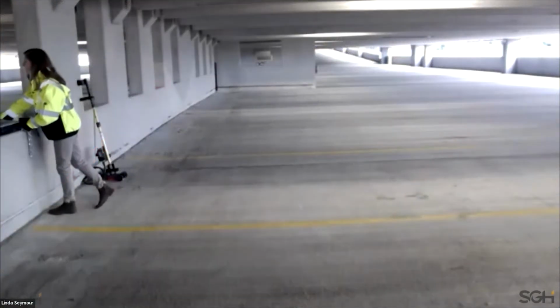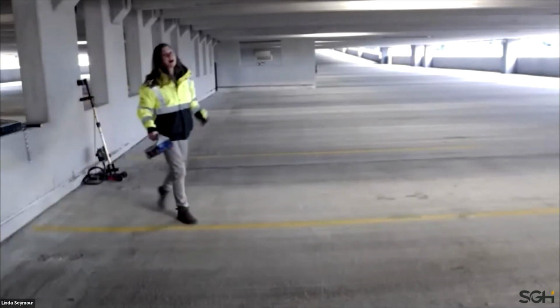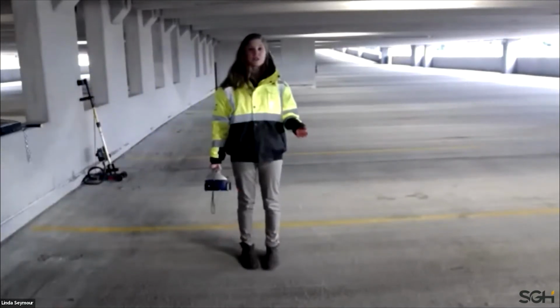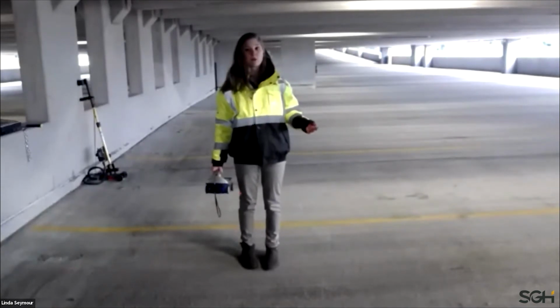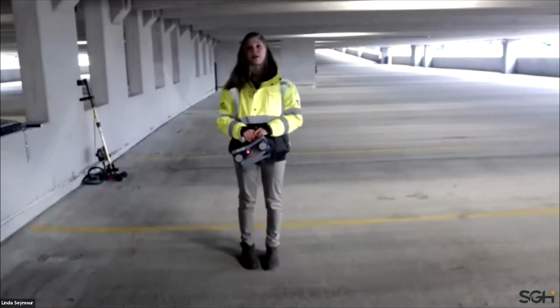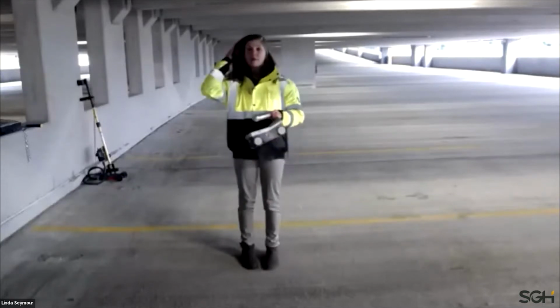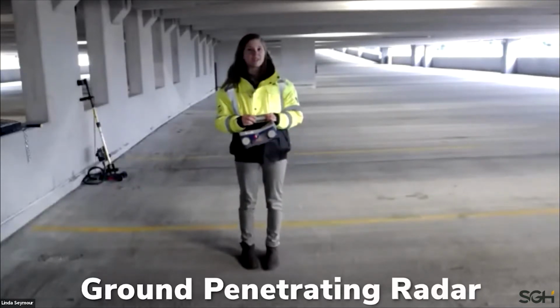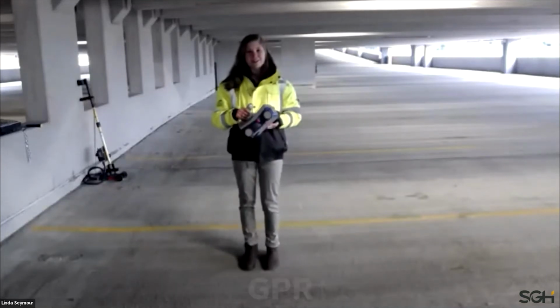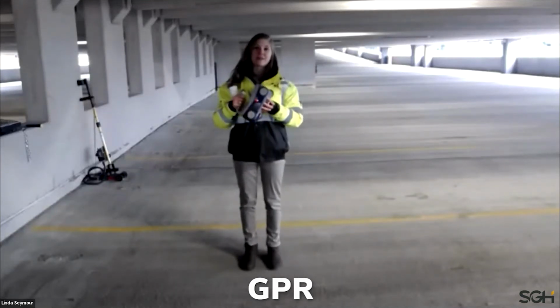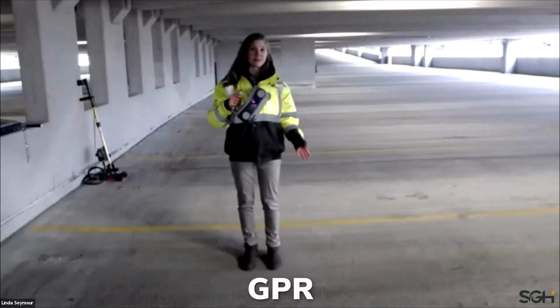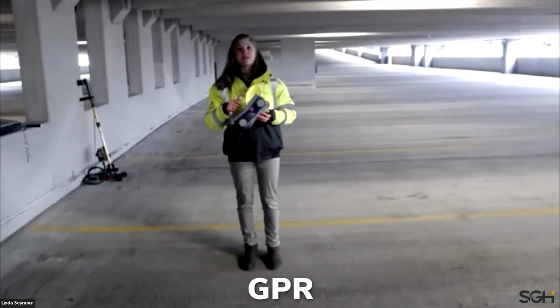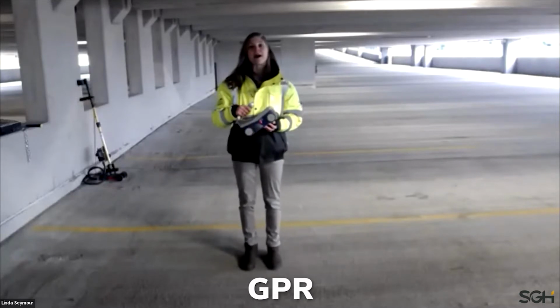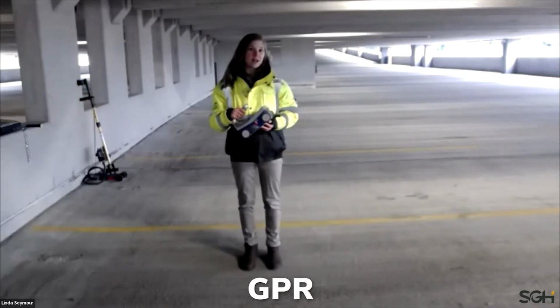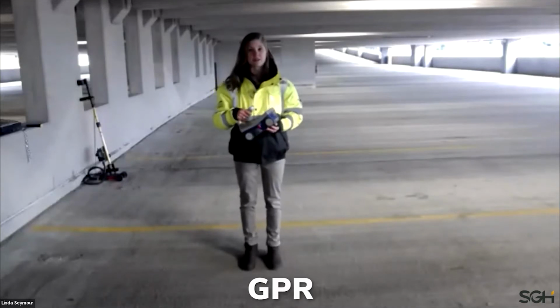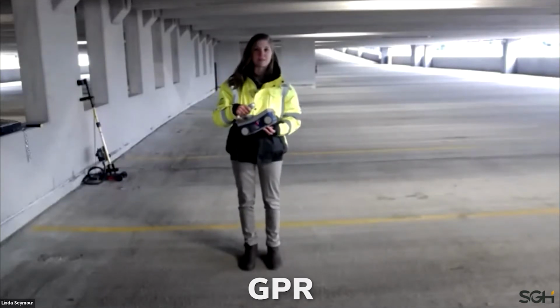Ultimately, our visual inspection and our sounding help inform where further non-destructive or destructive techniques might be required in order to understand what's going on in the concrete. One of the more common ways that we'll do this is with ground penetrating radar, or GPR. In ground penetrating radar, the radar is going to come out through an antenna and go into the substrate, in our case, concrete. Now, that radar signal is reflected back, and materials with different dielectric constants will appear as different colors on our data collection screen.